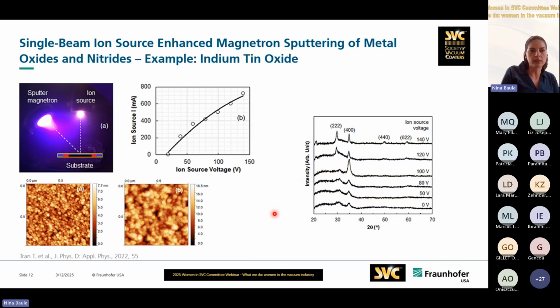Another example for magnetron sputtering now, so what I showed you before was an arc technology, is that we investigate a lot the single beam ion source enhanced magnetron sputtering, where in collaboration with one of our MSU professors who develops these ion sources, we try to enhance our magnetron sputtering, the material properties at the end, with this enhanced ion beam. And the idea is really to densify the film and have another basic knob that you can turn to change your material properties. So here you see an example of indium tin oxide, where you can clearly see that the crystalline properties of the material change with the ion source voltage.